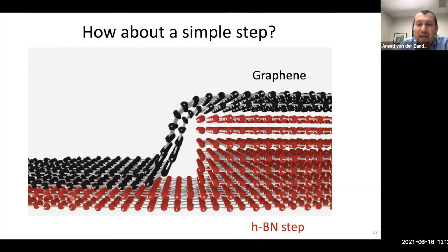The way we do it is by taking graphene and laminating it over atomic steps in another 2D material called hexagonal boron nitride. And what happens is, as I told you, the materials like to stick to each other. So the force of adhesion pulls the graphene down, and then the force of bending pulls it up. And what you end up getting is a balance, a shape that tells you what the mechanical stiffness is.